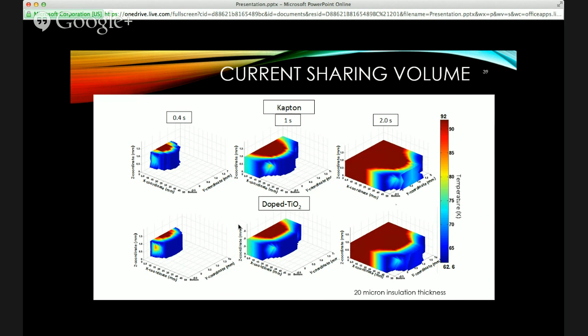And then, I'm not going to show it for all of them, but this is the breakdown. So I wanted to show a snapshot of the time periods. The one we just saw was at the 0.4 second mark. Then we moved to the 1 second mark, and then onward to 2 seconds. At that point, the temperature here doesn't actually show. And I'm sorry, these are for the 5 temperatures. This does not include the homogeneous section.